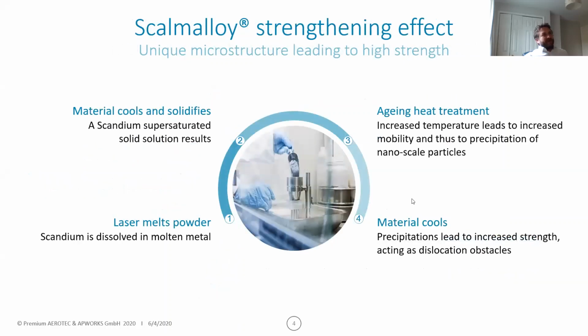So how does it work? I haven't really mentioned yet the chemistry that really makes it work, and that's the scandium addition. So scandium is kind of a magic element, which a lot of material scientists love the effect of scandium with aluminium, in that a very, very small amount of scandium has a very, very big strengthening effect on aluminium alloys. The problem that you have with this is scandium is very expensive, so you can only really afford to put a small amount in. And if you put a lot of scandium into an alloy, you need to have a very high cooling rate in order to avoid the scandium coming out of solution.